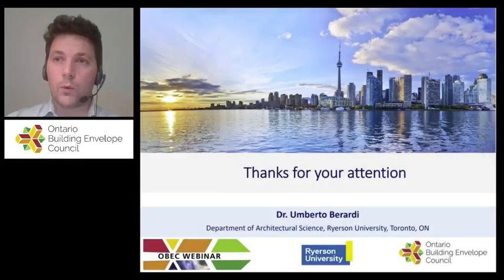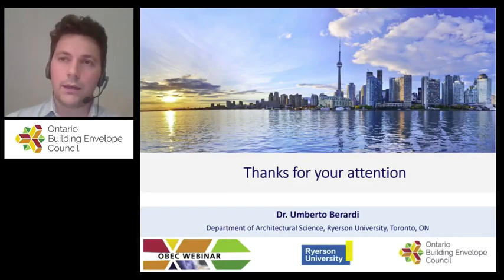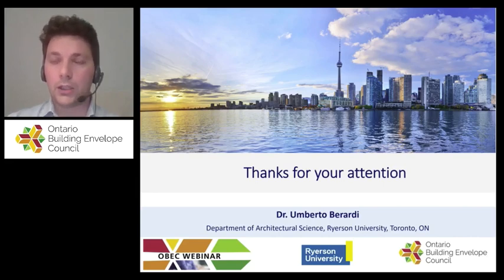So what happened in the polyurethane industry, just for those online who don't have a clear picture of it: the foam industry for polyurethane went from CFC to HCFC, and then HFC, and these days is going to the fourth generation of HFO blowing agent. So we have done tests with them, and I need to confess that both HFO and HFC, so both the fourth and the third generation of blowing agents, are quite okay. They don't have a significant detrimental effect on thermal conductivity at low temperature. They tend to follow a straight linear relationship with a trend that is typically around 0.0015 W/(m·K). So it's not only linear, so no significant low temperature problem, but also it is not really increasing too much at high temperature. So these two problems tend to be solved.